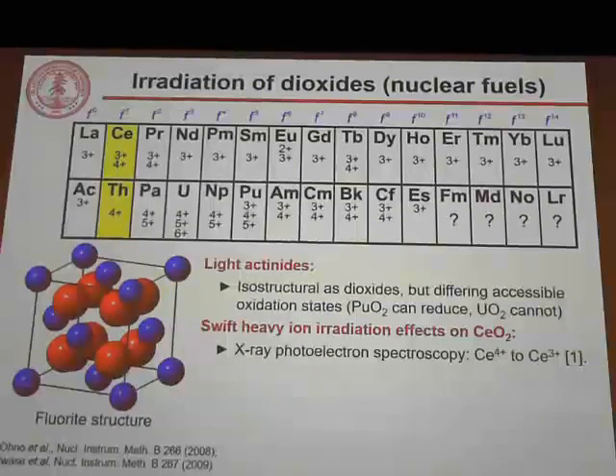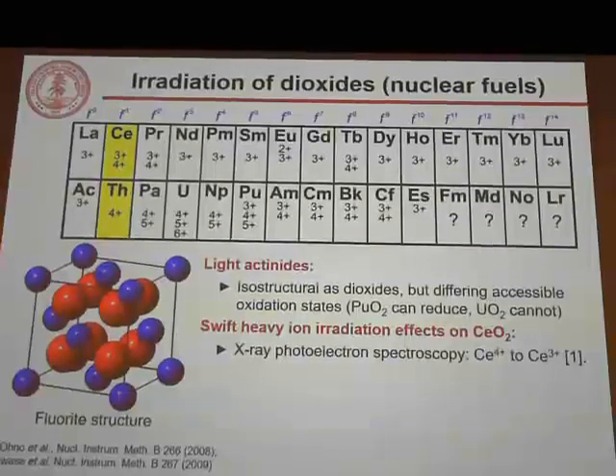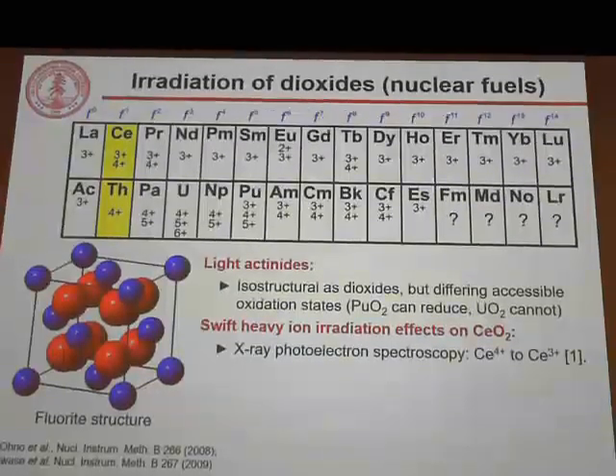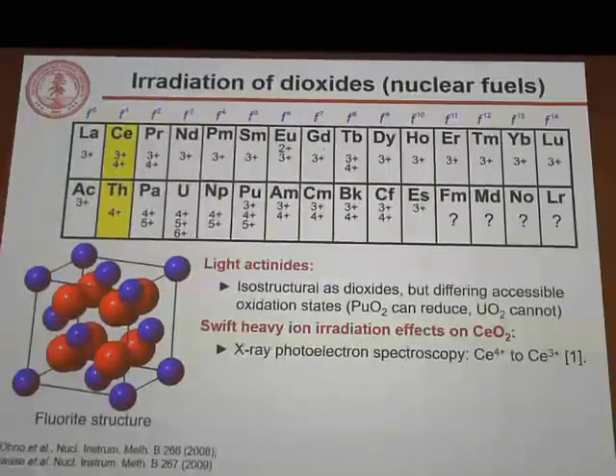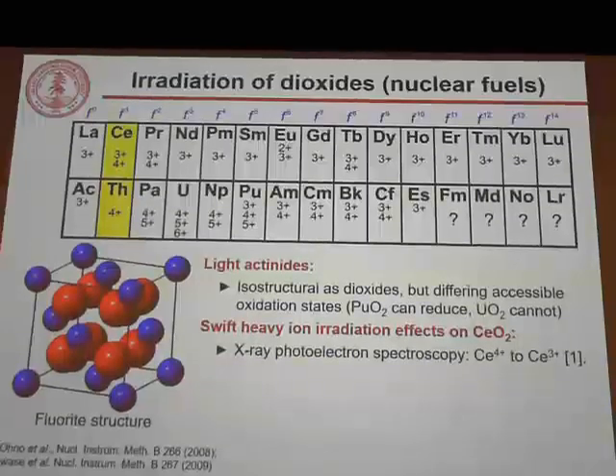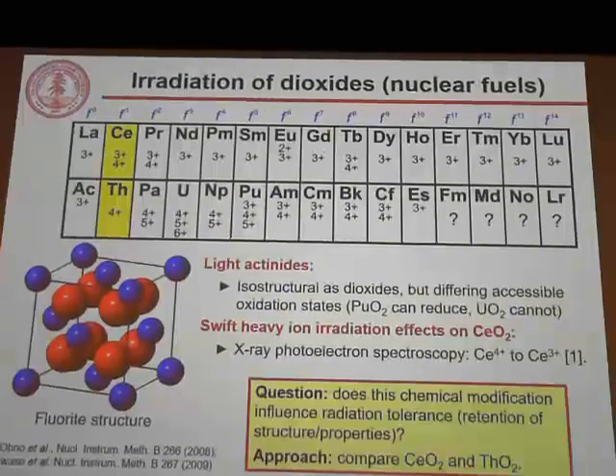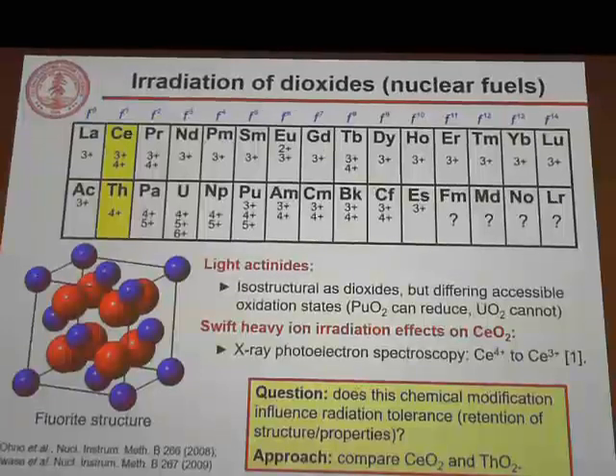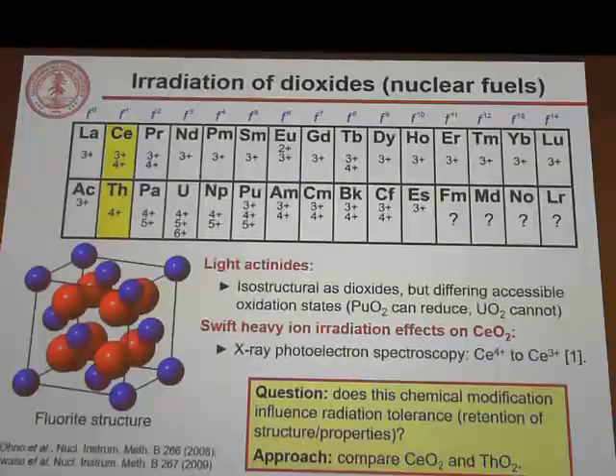And this might be important for the radiation tolerance of these materials, because we know from studies on the light actinide analog material, cerium dioxide, that irradiation with swift heavy ions causes reduction of tetravalent cerium to the trivalent oxidation state. And that's interesting because among these light actinides, some of them, like plutonium, have accessible trivalent oxidation states, and others, like uranium, do not. So this might cause a dramatic difference in the radiation tolerance or the radiation response of these materials. So the question I asked here was, does this irradiation-induced chemical modification influence the radiation tolerance of these materials, their ability to maintain their structures and to maintain their properties under irradiation?